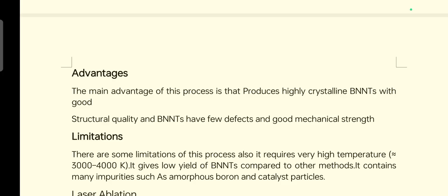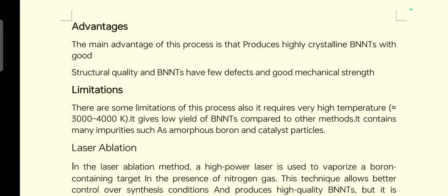Here are also some limitations, as all the processes have advantages as well as disadvantages. There are some limitations of this process. It requires very high temperature, 3000 to 4000 Kelvin. It gives low yield of boron nitride nanotubes compared to other methods. It contains many impurities such as amorphous boron and catalyst particles.